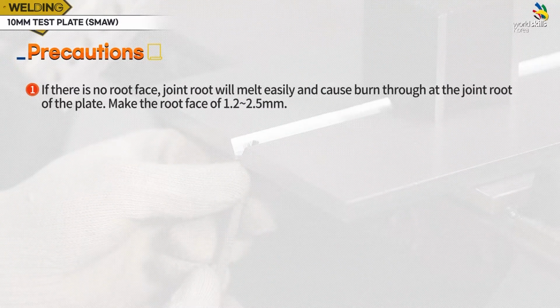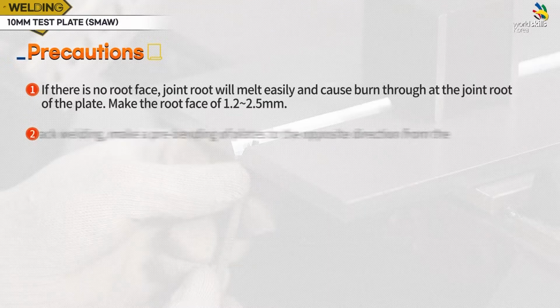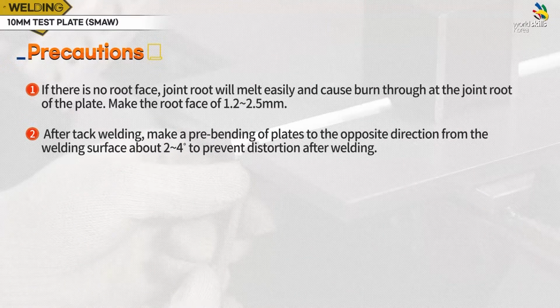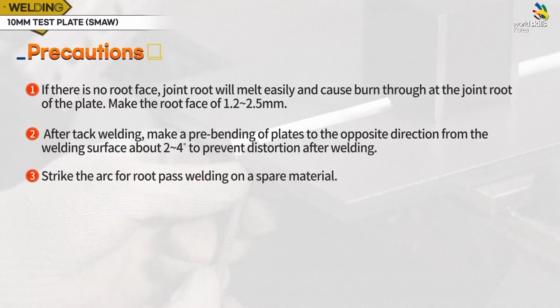If there is no root face, the joint root will melt easily and cause burn-through at the joint root of the plate. Make the root face 1.2 to 2.5 mm. After tack welding, make a pre-bending of plates in the opposite direction from the welding surface about 2 to 4 degrees to prevent distortion after welding. Strike the arc for root pass welding on a spare material.